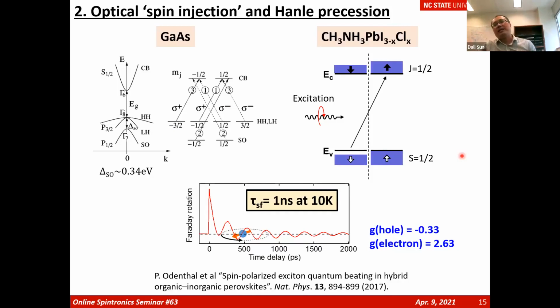So this work performed by Sarah Lee's group in Utah, using our material, the MAPbI3-xClx, iodine materials, chloride materials, is showing that using circularly polarized excitation, we're able to inject spin current into this band, into these materials, and by applying a magnetic field, you see very nice spin precession. You can measure the g values of holes, you can measure the g value of the electrons. We're showing a really precisely determined delta g between two particles, indicating a strong spin-orbit coupling formation in such hybrid perovskite structures.